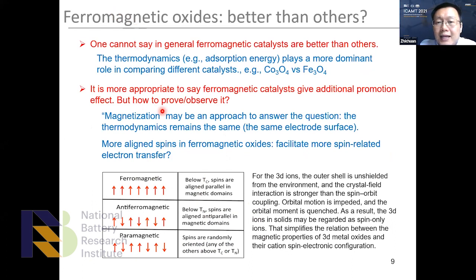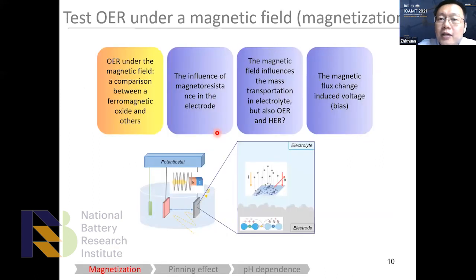So that means we need a catalyst with the same surface chemistry, without changing the surface chemistry. However, we need more spin alignment, or more aligned magnetic domains, in the ferromagnetic oxides. This is something like magnetization. In this way, we can see the magnetization degree change, and then correlate the activity result with the magnetization degree. In this case, we can prove the existence of such a benefit given by the ferromagnetic oxides. So then we magnetize the catalyst to test the OER under a magnetic field.